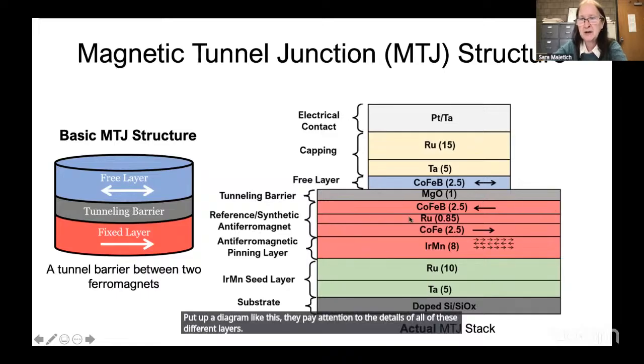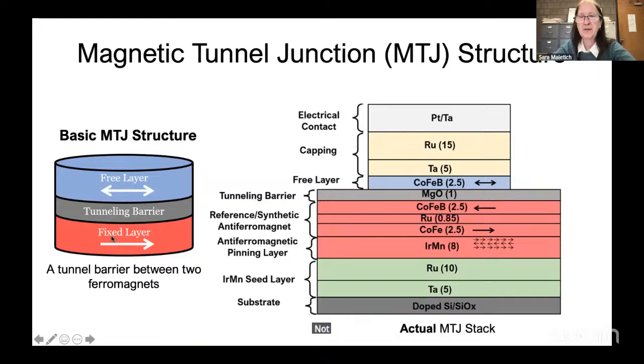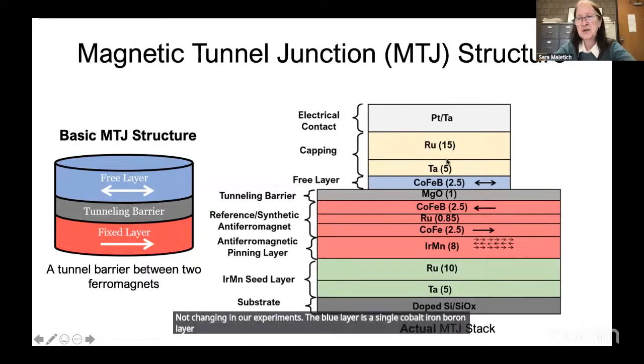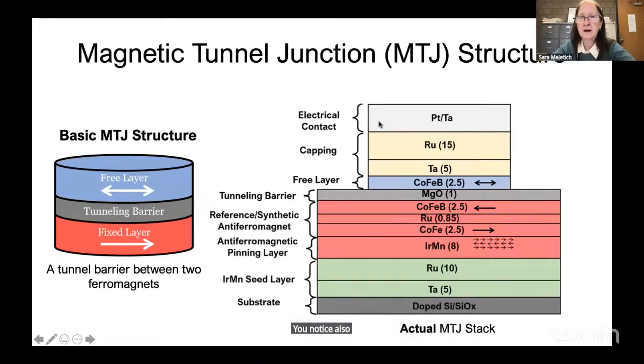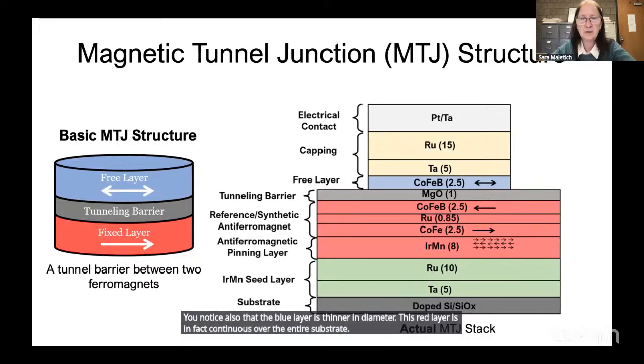This combination here shown in red is the fixed layer. The antiferromagnet iridium manganese helps to pin the ferromagnetic cobalt iron, which is in a synthetic antiferromagnet, again, in order to stabilize this so that this magnetization stays fixed. It's not changing in our experiments. The blue layer is a single cobalt iron boron layer, and it is switching back and forth during the experiments. You notice also that the blue layer is thinner in diameter. This red layer is in fact continuous over the entire substrate. I'll explain the reason for that.